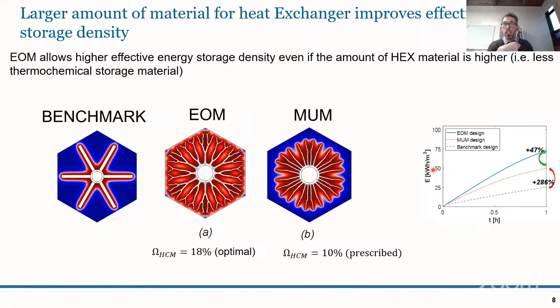energy storage, or energy retrieved per unit of volume, for the benchmark case and the topologically engineered case, where the energy output maximization leads to the structure that extends far deeper into the reactor cross-section, while the maximization of material utilization focuses on essentially maximizing and extracting the net effect use of the material that is closer to the proximity of the central pipeline that transfers the heat to the potential end users or to the source that charges the thermal storage.